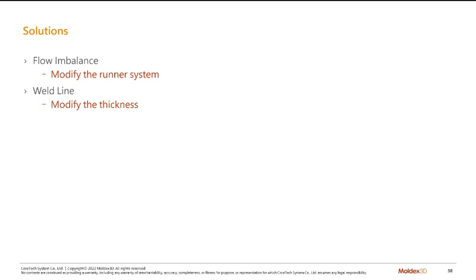They have an imbalanced runner system, which creates an imbalanced flow, and then the quality in each cavity is not the same. And they have weld issues, and it is related to the thickness design. If they can remove the sink features and make the thickness more uniform, they might be able to provide better weld line quality, and maybe they can fix these crack issues.